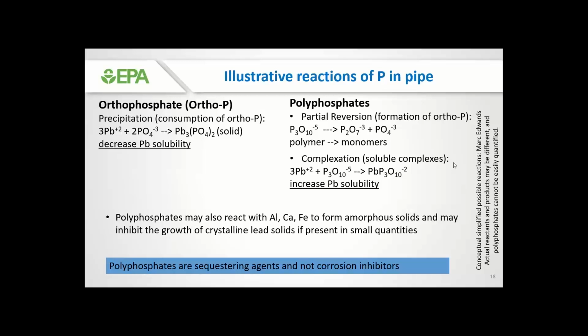The first one is partial reversion of the poly to ortho. So a small percent of the polyphosphate will convert from a polymer to monomers, and the orthophosphate that then forms will behave like the generic reaction on the left. But the majority of the polyphosphates, the remaining ones that haven't reverted, will actually react with the lead ions that were released to form aqueous lead complexes. So soluble species, not solids that precipitate out of solution, which increases lead solubility.